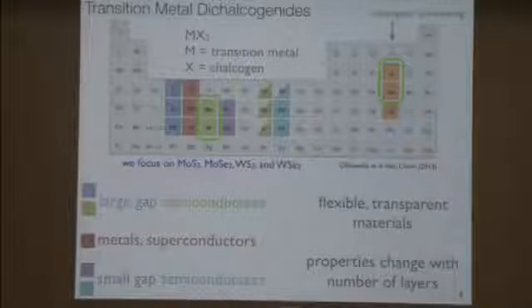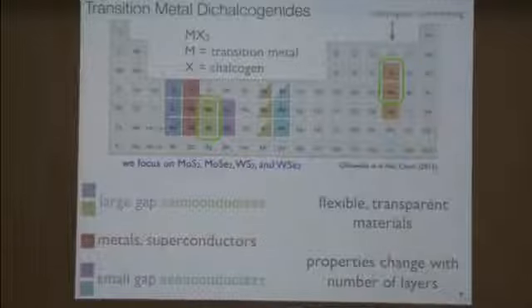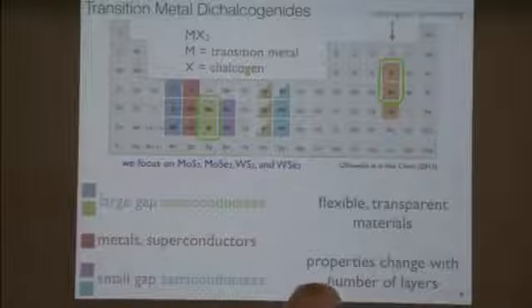And in general, for these layered materials, when they're thinned down to only a few atomic layers, they become flexible and transparent, which may have interesting technological applications. And in addition, the physical properties of these materials depend very sensitively on how many layers there are. So for example, a single layer of molybdenum disulfide has a 50% larger band gap than a bilayer of molybdenum disulfide.